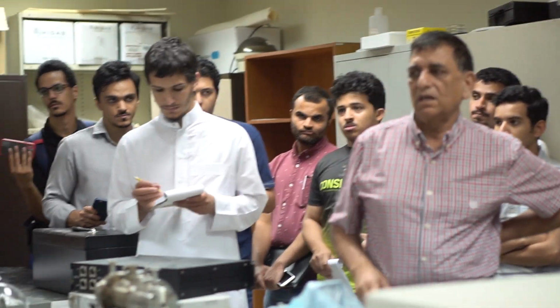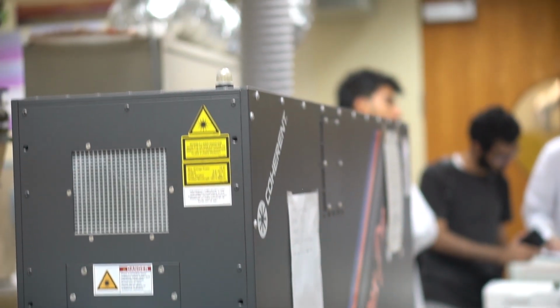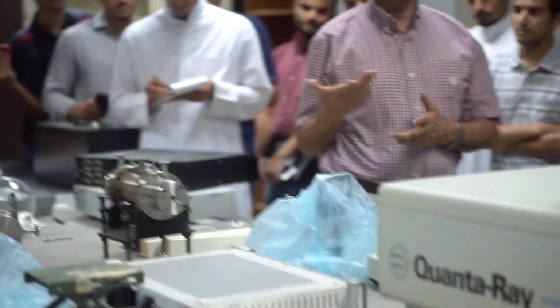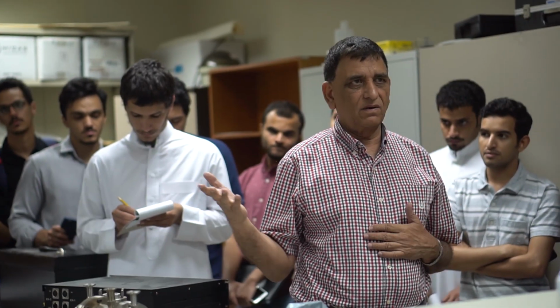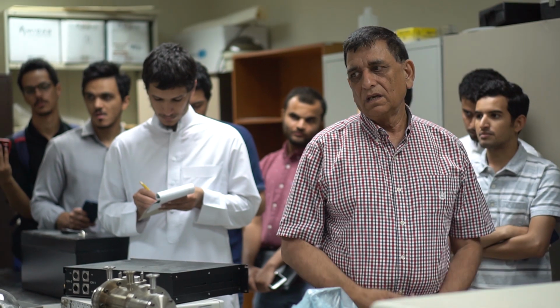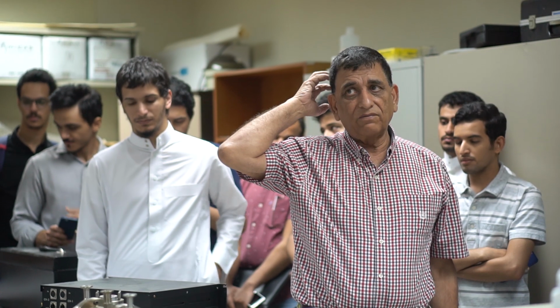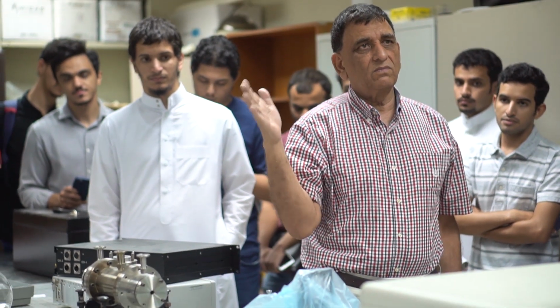So that's why we call it an excimer laser. The beauty of this excimer laser is the beam is almost 2 inch by 1 inch, while you saw a very small beam there. So that's why this laser can be used for many industrial applications. And what we are doing here is we use the same technique we use for ablation, but here we make films. We have a target, we focus this beam, we ablate this material and remove it, and on the other side we have a substrate, so we collect that material on the substrate.